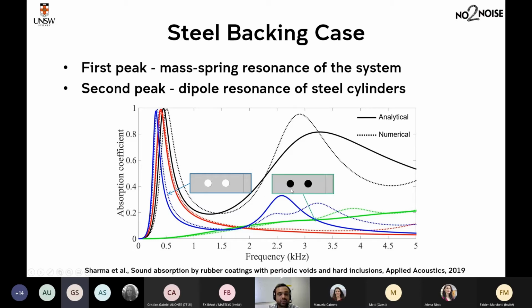This is when you have two hard inclusions. When you have two hard inclusions, you don't really have monopole, you don't really have the mass spring resonance. This is with a layer of voids followed by a layer of hard inclusions. Again, you see here, when you have voids, you have this first peak of really high sound absorption, but the dipole resonance does not happen. And again, the reason is the same. The layer of voids reflects all the incident sound wave.